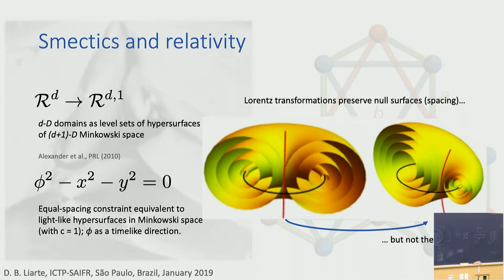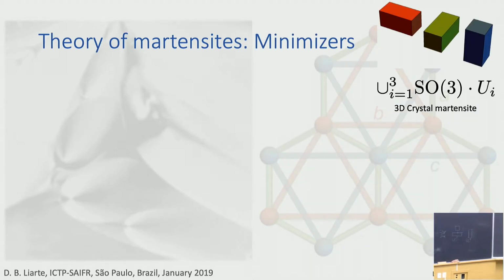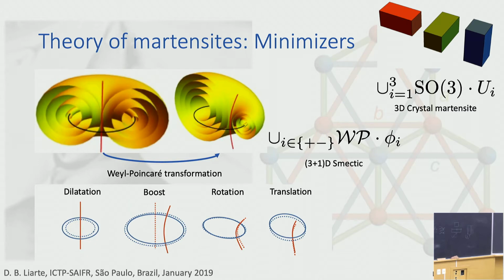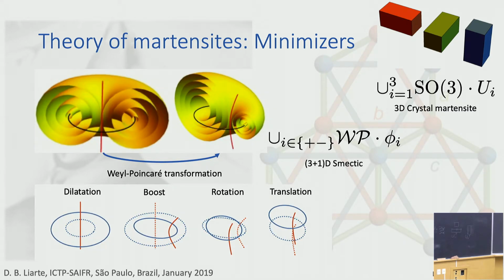So this is an interesting connection between Smectics and relativity, and it leads us to the third part of the theory of Martensites, which are the energy minimizers. For the crystal Martensites, after you have your three variants, you can rotate them and apply some general three-dimensional rotation, and you still have a minimum of the free energy. For the Smectic, you have a much richer group of symmetry. You can not only rotate them, you can apply a dilatation on your Smectic. You can apply a boost, and then you change your shape from this toroidal shape to this elliptic hyperbolic shape.